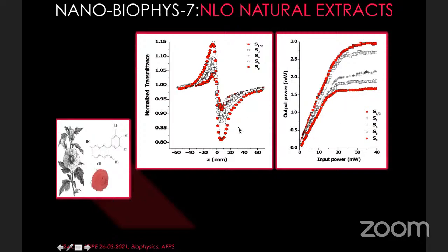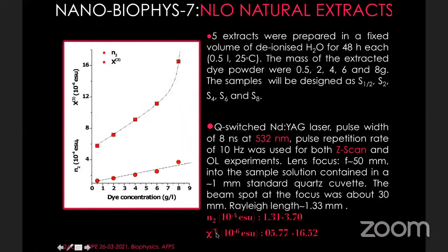And if there is an optical limiting, there is a nonlinear behavior. And running the Z-scan, he was able to get the chi-3, which is not negligible, 10 to minus 6 times these values. And the nonlinear part is not zero. It's certainly small, 10 to minus 4, but it is there.